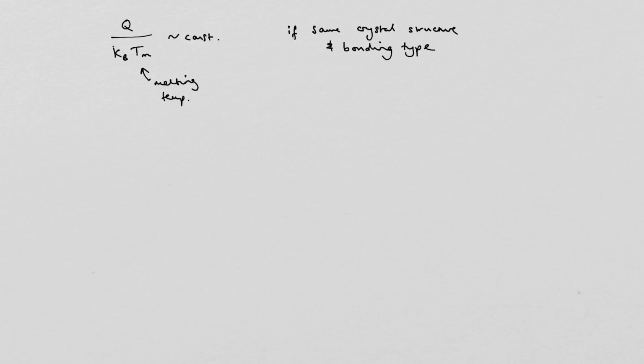Okay, and that constant, for example, is about 18 if we take the example of close packed metals, just for example.